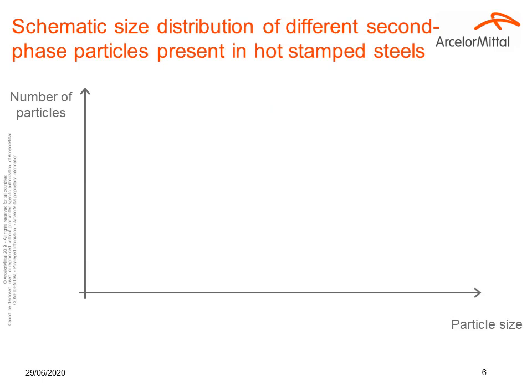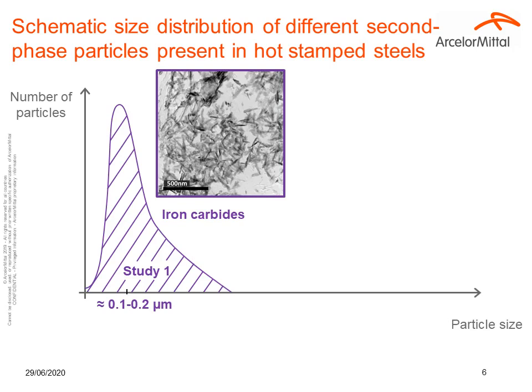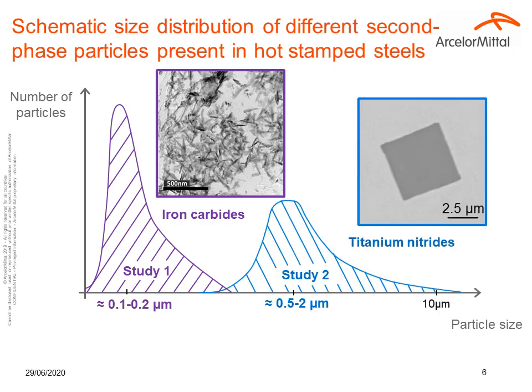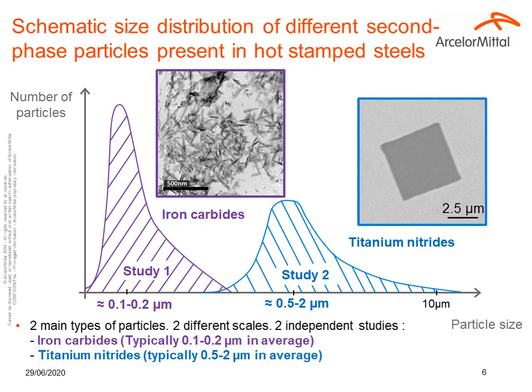Second phase particles can be represented via their size distribution. Here is a schematic size distribution graph between the number of particles and the equivalent particle size. The first distribution is a representation of the iron carbide with an average size between 0.1 and 0.2 micrometer. Our study number 1 will focus on this type of particle. Study number 2 will focus on the effect of titanium nitride inclusion, whose average size is about 0.5 to 2 micrometers. So we use two different studies to investigate the effect of this population on crash ductility.